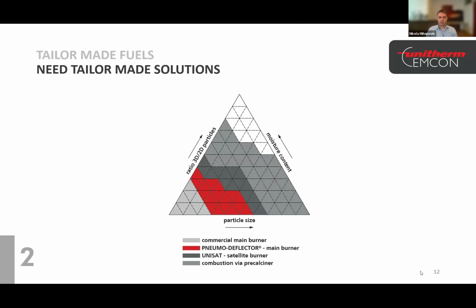As mentioned earlier, shortly after our focus shifted to rotary kiln process in cement industry, we began delivering burners with secondary fuel firing capabilities. Initially, this meant a simple pipe through the main burner, but since then, we have been dedicated to finding solutions to increase volume of secondary fuel that can be fired through the main burner by influencing particle behavior when exiting the burner. Our innovation and proven solution in this development is pneumo-deflector, which has been in use for more than 1 decade.